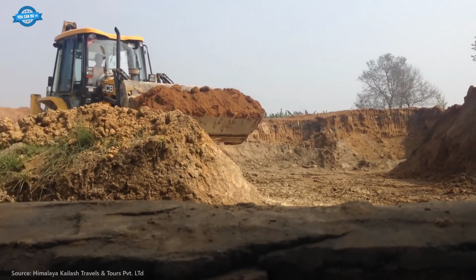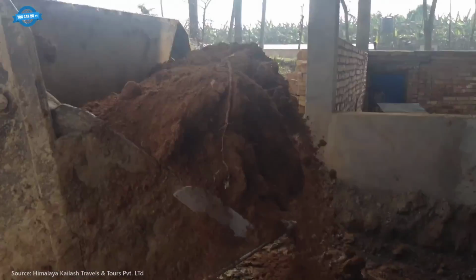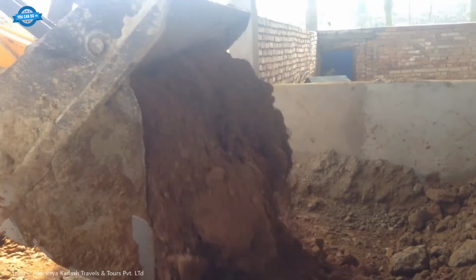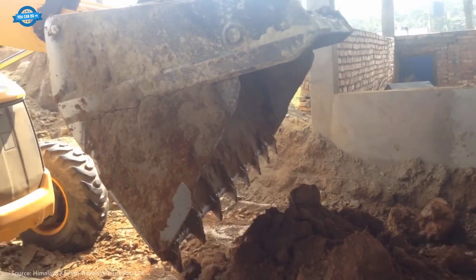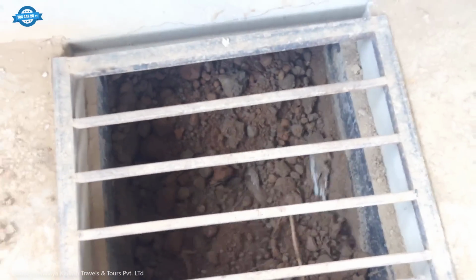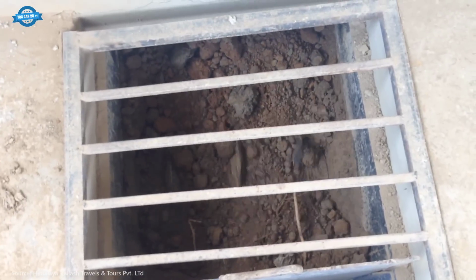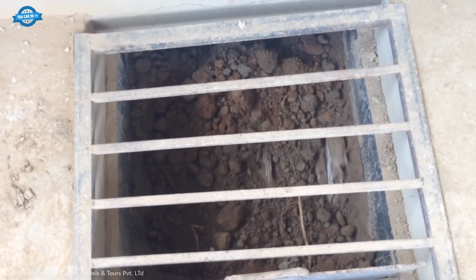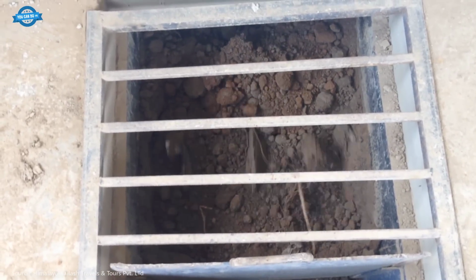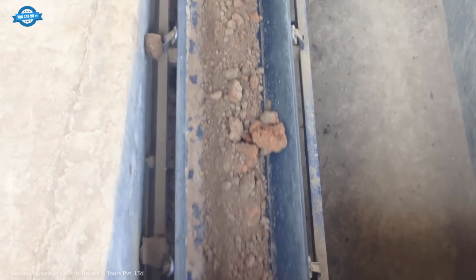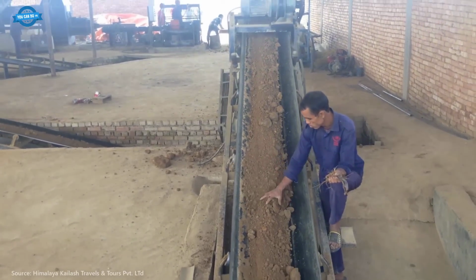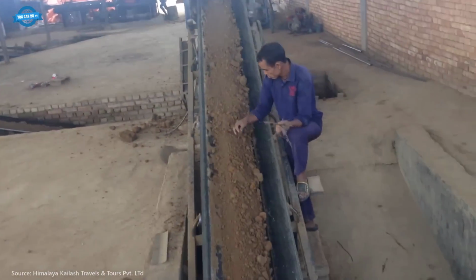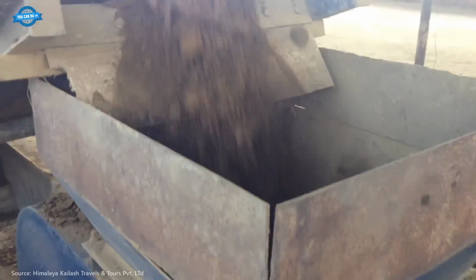Traditional brick production in Nepal relies on manual processes and primitive kilns, such as the bull's trench kiln. This method requires significant labor and consumes high amounts of coal, about 25 to 30 kilograms of coal per 1,000 bricks, leading to higher pollution and lower efficiency. Daily output typically ranges from 10,000 to 15,000 bricks, with inconsistent quality due to manual shaping and firing.